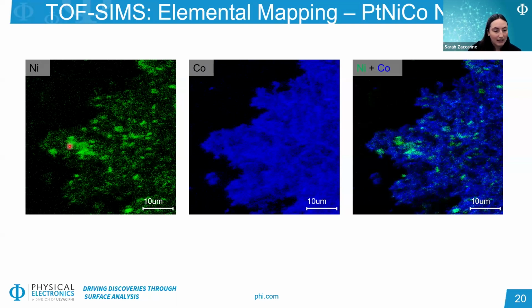So this indicates that in this case, the nickel is the coating on the nanowire template. And this nickel coating does not look like it's very uniform across the majority of the cobalt nanowires. And you can see that in particular in this overlay of these two elemental maps. We see clear regions with brighter nickel and some without much nickel, and it's not really tracking very uniformly across the wires. So comparing this back to a few slides previous, the platinum map was also fairly low concentration, but it generally looked a little bit more uniform as a coating on the nickel nanowires than this nickel does as a coating on these cobalt nanowires.